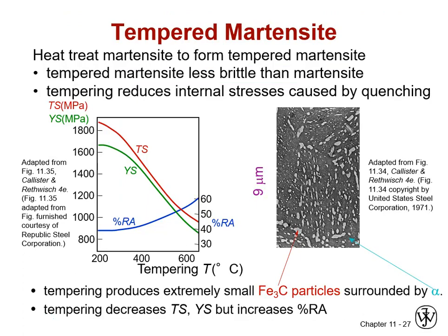And this gives you a little bit of a semi-quantitative estimate of what happens when you temper martensite. Again, we never want to use it in the untempered state unless we have an application where we would be okay with a ceramic, which is pretty much none for monolithic materials. So you can see how as we increase our tempering temperature for a given time, we start marching from the left to the right on our left-hand side diagram. So we're going to drop our yield and tensile strength as we release the strain energy in that metastable body center tetragonal lattice, and we're going to increase in our reduction in area, which is an indicator of fracture toughness.